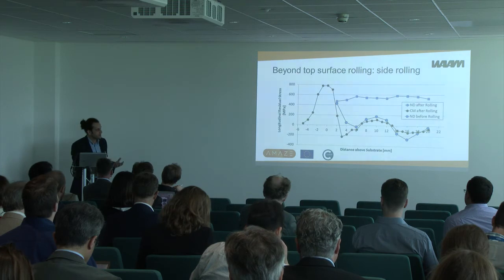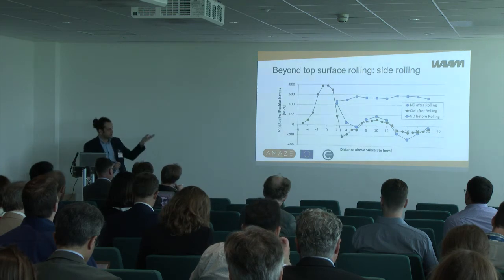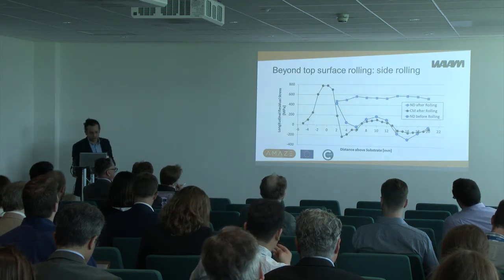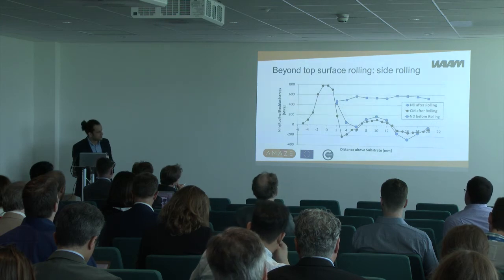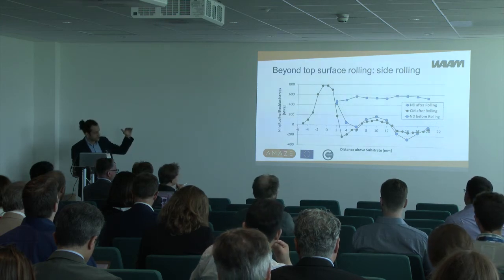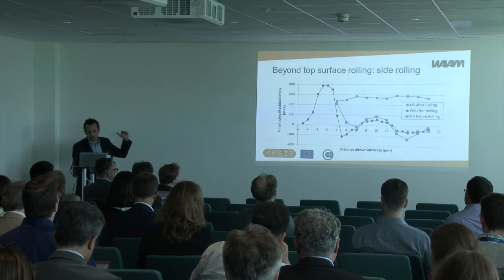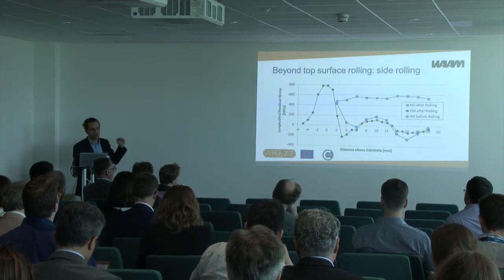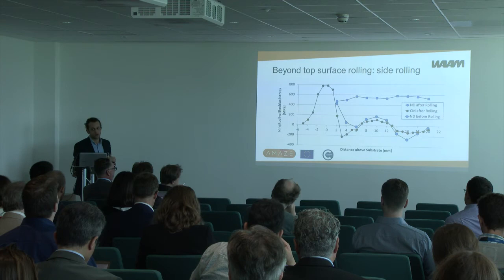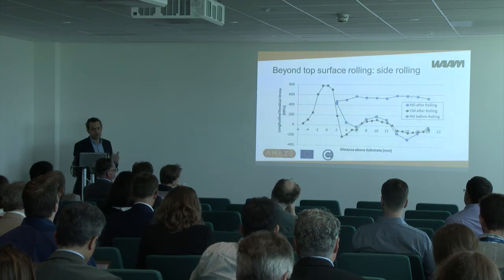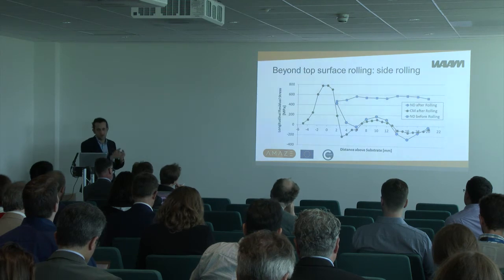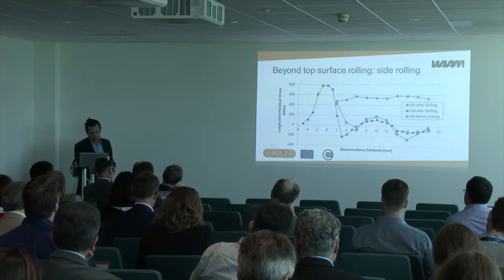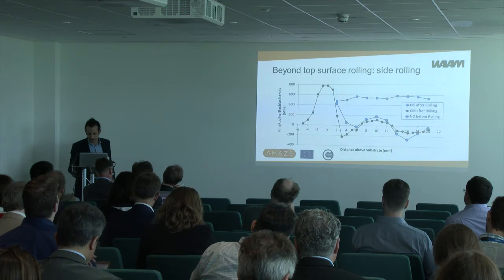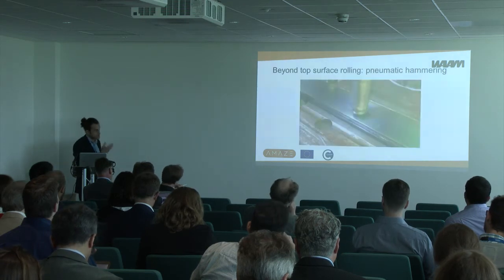And the idea that this works much better is demonstrated by the fact that when you're doing rolling from the side, the residual stress on average is pretty much 0. And in fact, with this method, we were capable of producing parts that had no distortion. The obvious drawback of this approach is that if you're coming towards an intersection, then you can't really go ahead with the pinch roller. And so again, there might be the need for a different process, and I will show you later. And actually, it's this one.